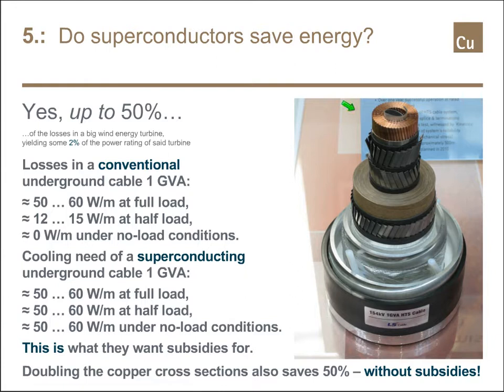As an aside, if you look at such a high voltage superconducting cable, it looks very similar to a conventional cable. You have a copper core here, which takes over the current in case the cable should become overloaded or too warm, and then the superconductivity breaks down. Then for a short moment, until the current is attenuated, it has to flow through the copper wire. The actual conductor is this here. This is one phase, this is the second phase, and this is the third phase.